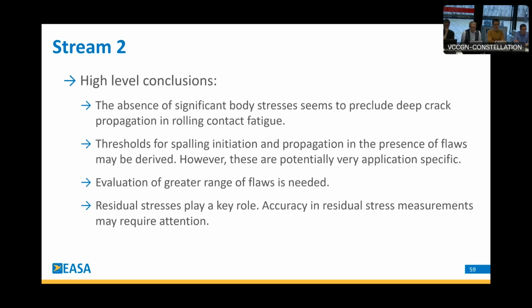And moving on into stream 2, I would like to start with some high-level conclusions. So first, I think it's reasonable to conclude that in the absence of significant body stresses, so stresses within the whole section of the integrated bearing race, it seems that that's enough, or should be enough, to preclude deep crack propagation in rolling contact fatigue, and as such prevent through cracking and rupture of the part, at least when due to this failure mechanism.